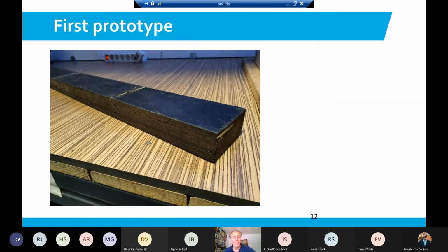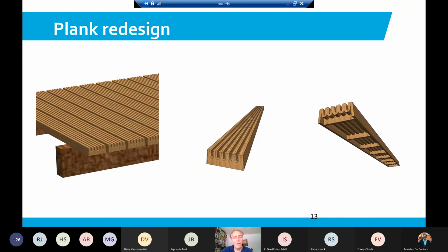First prototype we produced, this was not with a mold, it was with a simple mold, and we glued the elements together. And what we're doing at the moment, we're redesigning this plank. One redesign is with the pre-pregging method in mind, and the other one is with the bulk molding compound. So with the bulk molding compound, for instance, at the right side, you can see you have a lot of form freedom. So it's easy to make a product with lots of ribs, and don't put material where you don't need the material. So to optimize the use of material, to try to beat tropical hardwood in a value over price way. So that's what we're doing at the moment.